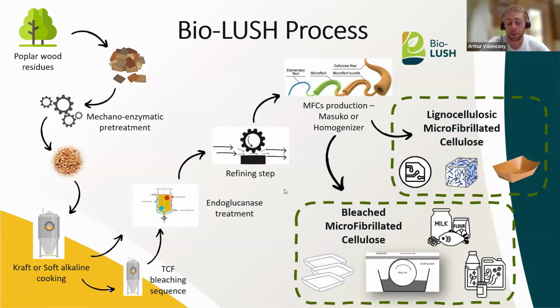And the next step here is an endoglucanase treatment that will target the glucose part of the cellulose, and it will improve the next step, which is the refining. So we are working here with a conventional low consistency refining of the pulp to produce at the end microfibrillated cellulose by different ways, with Masuko or homogenizer. So it's grinding or homogenization. We are also comparing the two different processes.